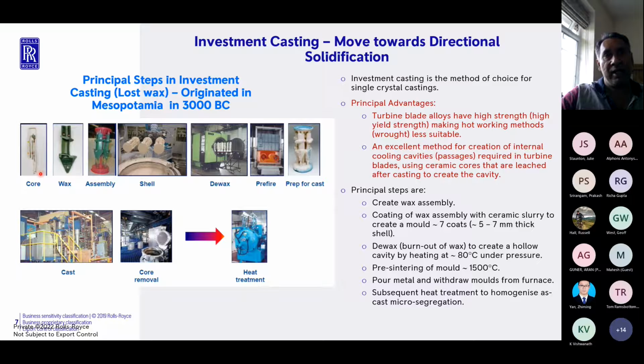And the gap between the ceramic shell and the core is effectively empty, and that's the region into which you pour the metal. Then once you have burnt off the wax, you pre-fire the molds just to basically strengthen them. So in other words, a bit of sintering, because these are kind of green in this condition. You then pour metal from the top of the mold that fills up these cavities, and that's the end of the casting process. But remember, when you finish the casting process, you've got metal, but you've also got this core in between. So you don't have any hollow cavity to begin with.